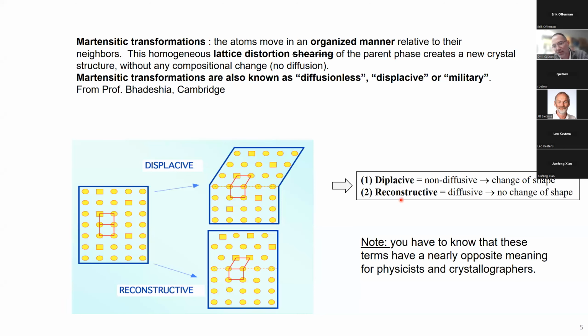The opposite is what we call a reconstructive transformation, which is purely diffusive, and there is no shape change. It means that we can form a hexagonal lattice, as is the case here, but then the position of the atoms cannot be traced back. It's impossible to know where this square atom comes from or where this round atom comes from. It's purely diffusive and not a coordinated transformation. Be very careful with this terminology, displacive and reconstructive, because if you speak with a physicist or a crystallographer, it has nearly the opposite meaning. I will not detail it here, but be very careful with these terms.